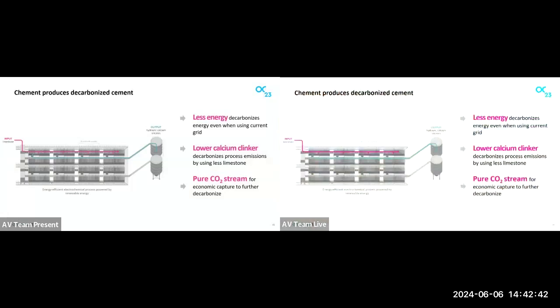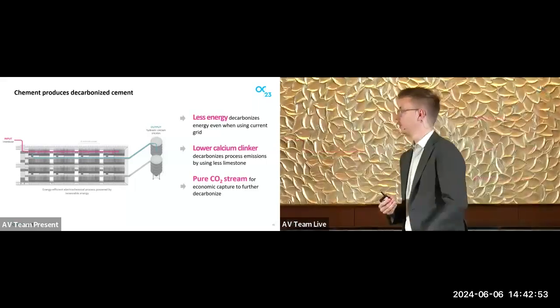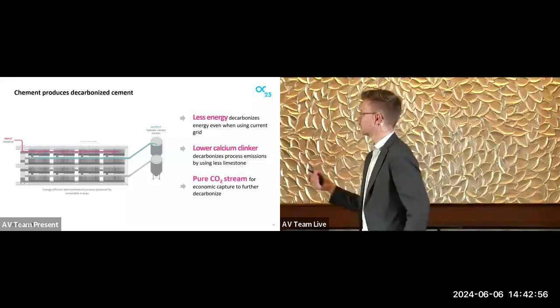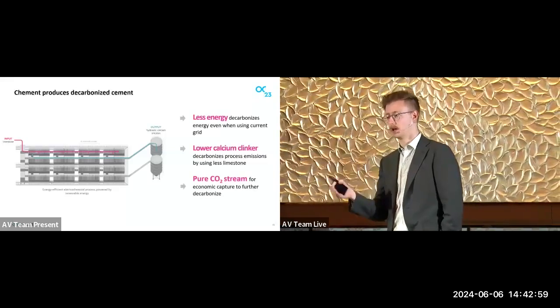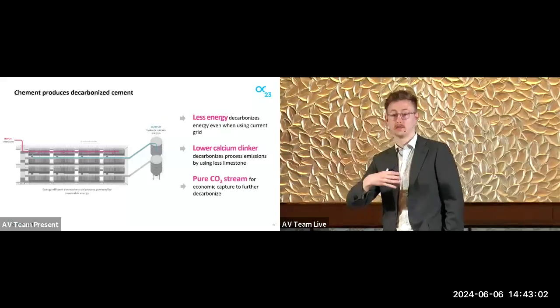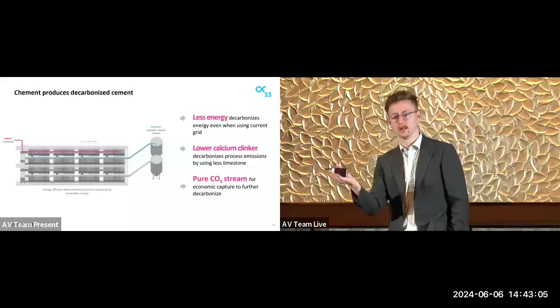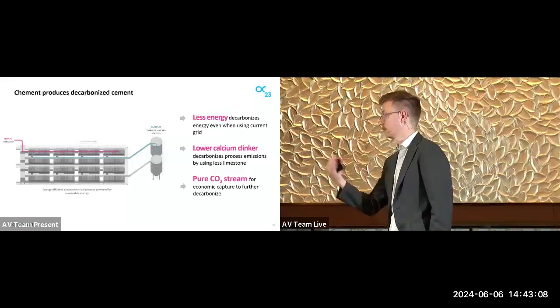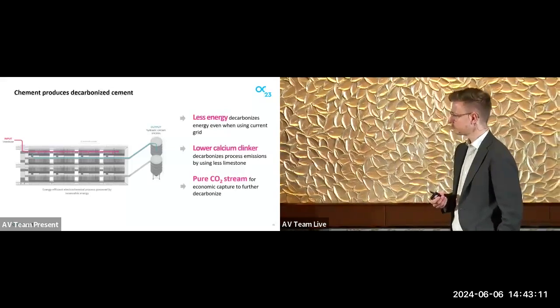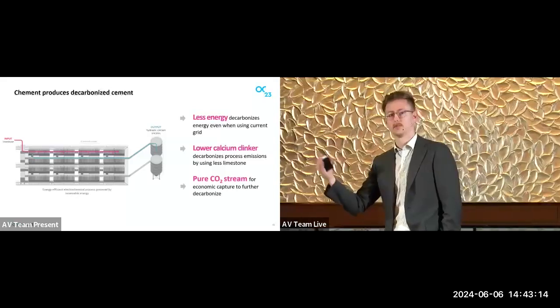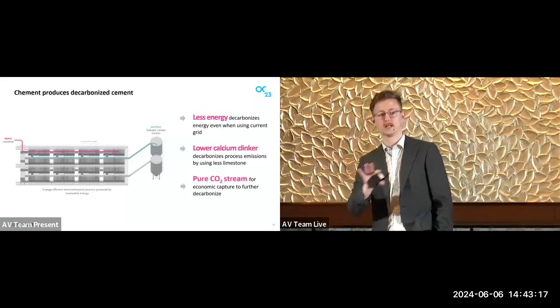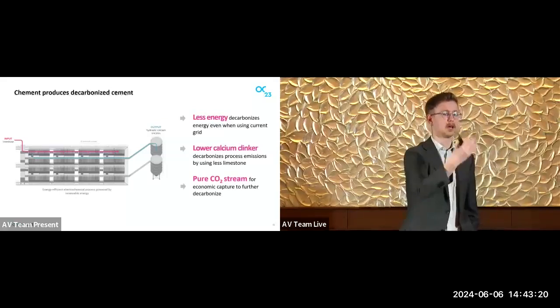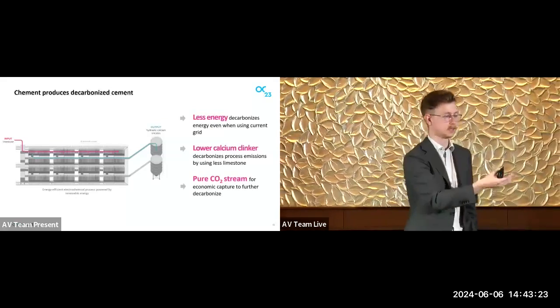And so we've come up with a process that's more energy efficient. So if you're using grid electricity, you could still decarbonize your energy compared to a kiln today. And of course, if that's green electricity, you can get that down to 0. The output of our process is a lower calcium content calcium silicate. So even if we're using limestone, we're using less limestone, so we can decarbonize the amount of direct emissions that come from decomposing limestone. And then the last part is if we want to go from a massive reduction of CO2 to zero, the remaining emissions from calcining that limestone are coming off in a pure stream or direct separation.